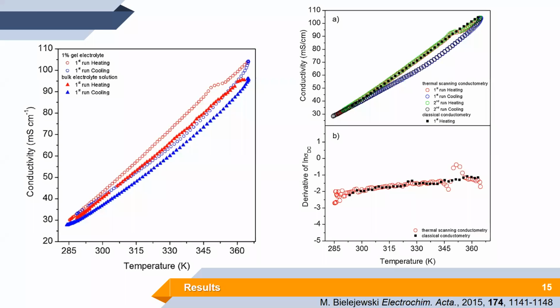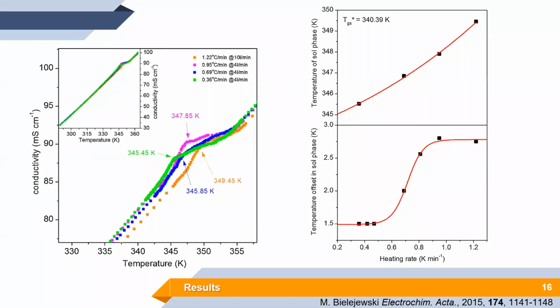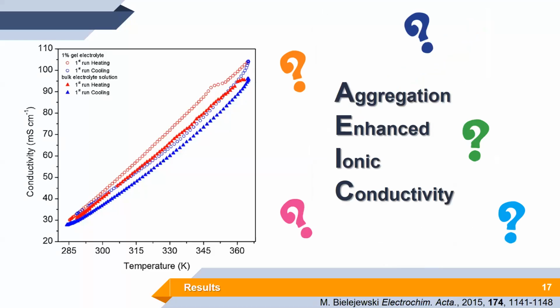This is very well seen when we analyze the derivative of the conductivity. You can see that the standard conductometry actually has the same behavior except the anomaly. So everything is fine from the physical point of view, only the method is not sensitive to this structural phase transition. This method allows us not only to see when the system starts to flow, as we call it, but it is also possible to determine the phase transition temperature, which is very important for applications. Okay, but enough about this. So the inspiration was to find the origin of this enhanced conductivity and try to understand it.